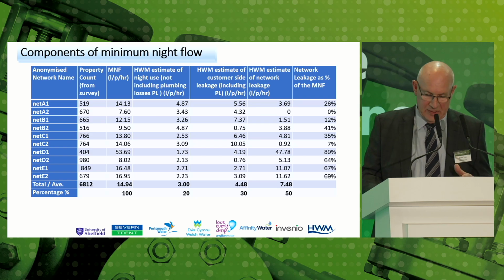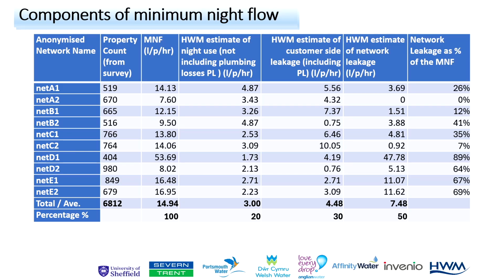I've tried to collate all of this information into this table, which obviously there's a lot to take in here in the time that I have available. But if we look at the totals and the averages near the bottom, we can see that of the water that's going into the DMAs, 50% of it is leakage or unaccounted for water on the water company network, mains and comm pipes. 30% of it is customer side, and 20% of it is night use within the DMA. So those are ballpark figures, but you can see in the right-hand column how variable that figure is.